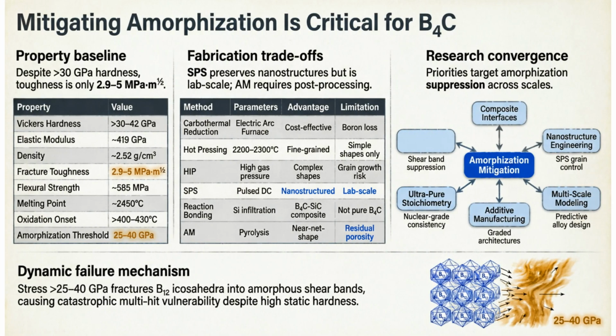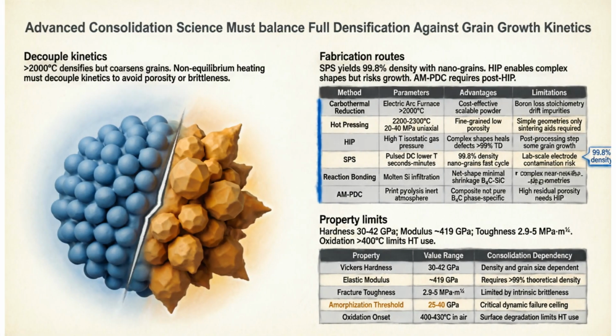By using DFT and molecular dynamics, researchers can now simulate nanosecond scale dynamics, capturing how amorphous bands nucleate at twin boundaries under high-stress conditions. Looking at fabrication trade-offs, we see that while SPS preserves critical nanostructures, it remains a lab-scale process, highlighting the need to bridge the gap between small-scale purity and large-scale manufacturing.